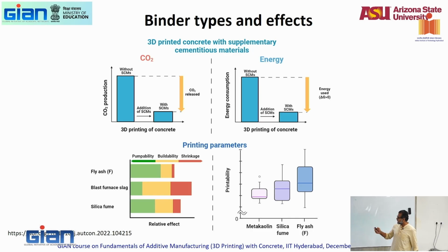Now, binder type. So if you want to start with packing, you talk about binders. What type of binders, right? So it'll be a good time to talk about binders that you will use. Most of the time, your 3D printed concrete will have a high binder content, correct? You are talking about 800 to 1,000 kilograms per meter cube of cement. Extremely high value. You don't really have to do that. You can drop it by 50% straight away. You can get to about 50% replacement of cement with some other materials if you know the way to control particle packing and rheology, right?